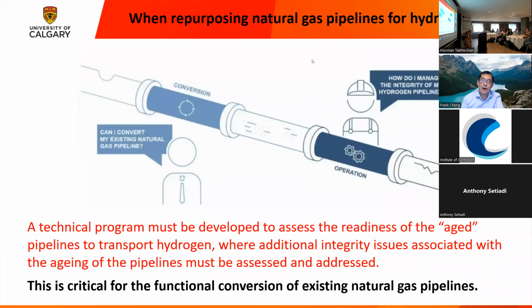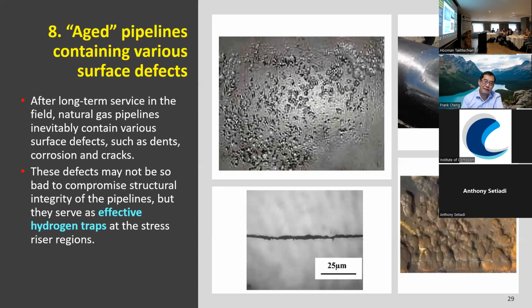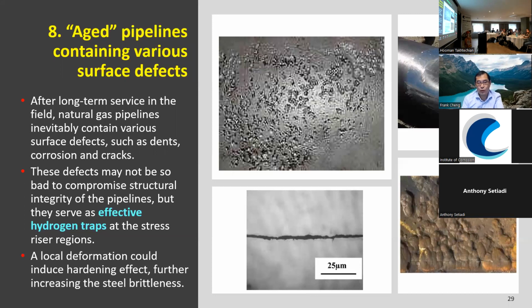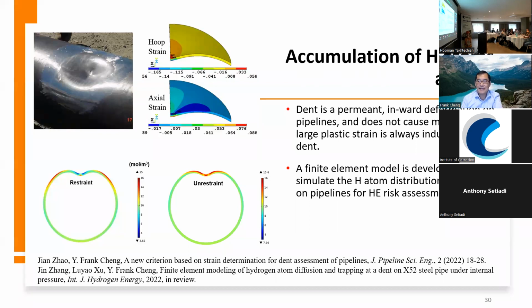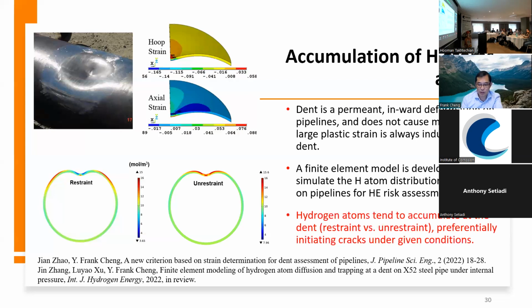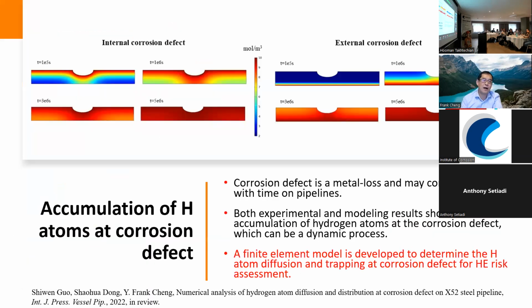And when we use aged pipeline to transport hydrogen, we also have additional challenges we have to overcome before we convert the pipeline to hydrogen service. The first thing we have to realize is that after long-term service, the natural gas pipeline usually contains dents, corrosion defects, and micro cracks. These defects tend to be effective hydrogen traps because of stress concentration. So we have to develop a technical assessment program to evaluate how effectively these defects trap hydrogen atoms. For example, if the pipeline contains mechanical dents, our simulation results tell us that hydrogen atoms will tend to accumulate at the dents, making the local hydrogen concentration reach a high level. The same results also apply for corrosion defects.